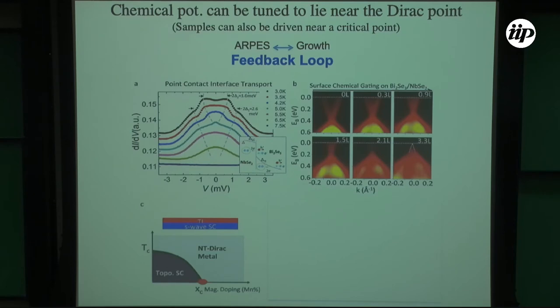Yeah, definitely. So then our next try was on MgB2. It's not necessarily as correlated as cuprates, but MgB2 at least has higher TC, 39 Kelvin, right? So we wanted to see if we can see topological superconductivity at 40 Kelvin. This is like 7 Kelvin.